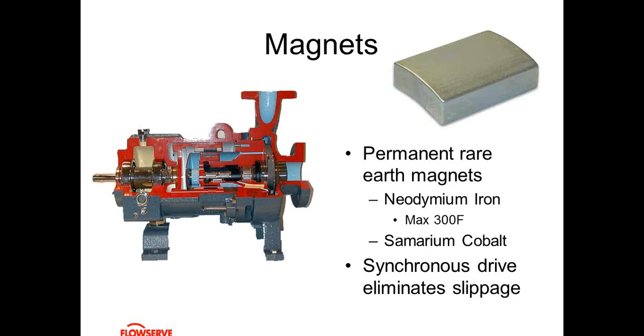So for those higher temperature applications, you go samarium cobalt. Samarium cobalt's a 5 to 20% price adder on any given size pump, depending on manufacturer. So it certainly is a little more of a rare material and more expensive, but on those higher temperature applications, samarium cobalt really is the magnet of choice. It is synchronous drive, so even though there's an eddy current loss when it goes through the can, you don't have slippage, all right? So if your outside magnet is running 1,762 RPM, then your inside magnet, and hence your impeller, is running 1,762 RPM.